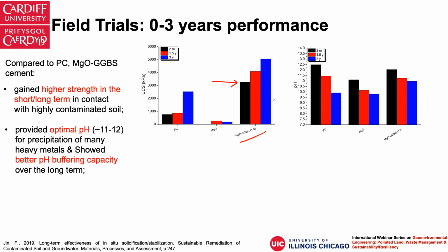And in terms of the pH values, as I just mentioned before, although the Portland cement gives a very high initial pH of around 12.5, over the years under carbonation and rainfall infiltration, the pH values decrease significantly to below 10. On the other hand, although magnesia GGBS cement has a lower initial pH value, in the end it stabilized almost at 11. So that is very good for soil stabilization, solidification.